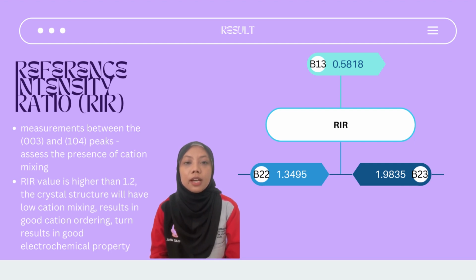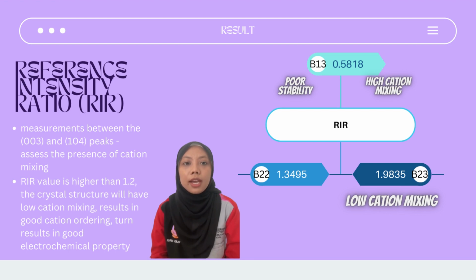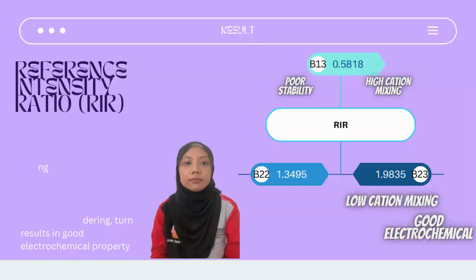Based on the result, the RIR value for B13 is lower than 1.2, which indicates higher cation mixing present in the crystal structure, implying poor stability. The RIR value for B23 is 1.9835, which is higher than 1.2, implying the material has lower cation mixing and has the potential to show good electrochemical behavior.